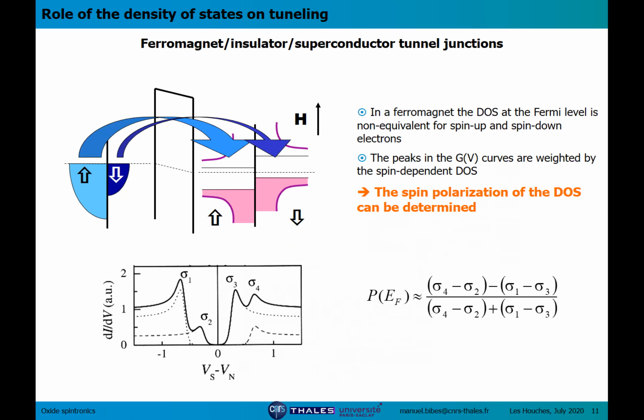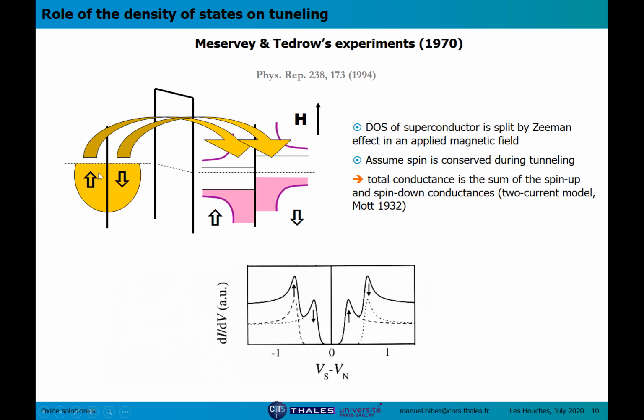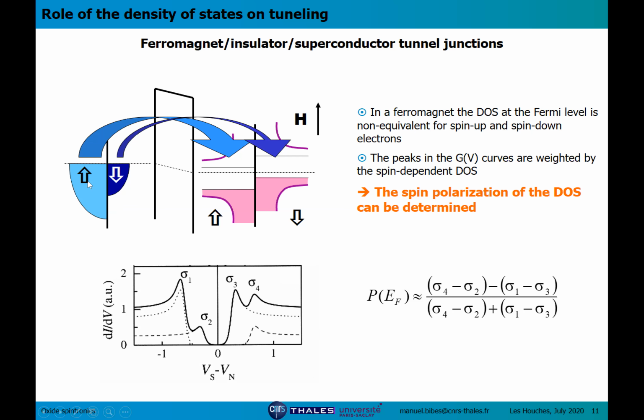And now, if instead of using a normal metal, let's say a paramagnetic metal like aluminum or gold, you use a ferromagnetic metal, then things are going to be different and very interesting. In this case, the amount of electrons tunneling with spin up or spin down is not going to be the same, because in the ferromagnet you have a spin polarization of the density of state at the Fermi level. So here, for instance, you're going to have more spin up than spin down, and so more current coming from spin up than from spin down. And so these 4 peaks, which were equivalent 2 by 2 because of the equal number of spin down and spin up states, are not going to be equivalent anymore when the metal is a ferromagnet. And so you're going to have this kind of curves.